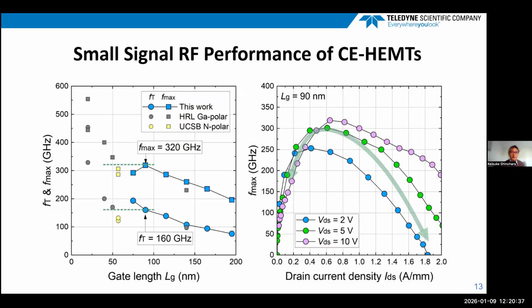So this is the small signal RF performance of the charge-enhanced HEMTs. On the left, I plot fT and fmax as a function of the gate length. With a relatively long gate length of 90 nanometers, we achieve an fT of 160 gigahertz and fmax of 320 gigahertz. And on the right, I show fmax as a function of drain current density, and the green arrow represents the fmax value along the resistive load line. So this device keeps a high fmax along the resistive load line, which improves the large signal gain.